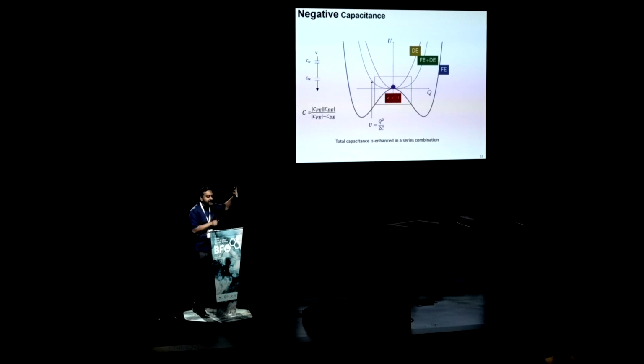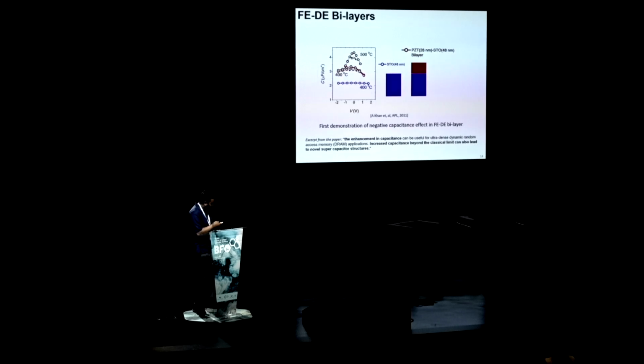You put two capacitors in series, capacitance should go down. That's what the textbook says, but in this case, the capacitance goes up. So our first experiment came out in 2011, where we put strontium titanate, that is a dielectric, and on top we put a PZT, and we actually saw that the capacitance is going up in these systems, showing that the ferroelectric is working like a negative capacitance in this system.